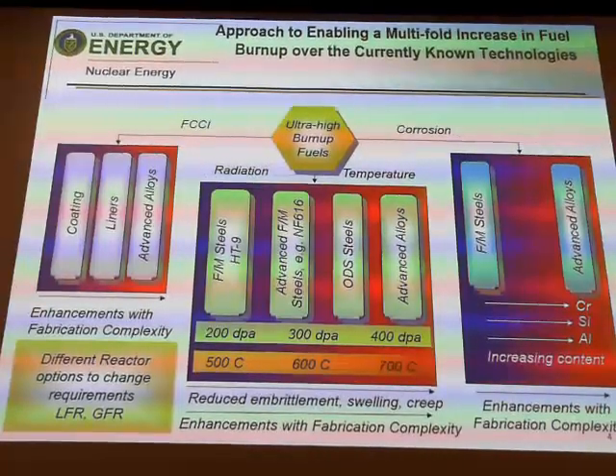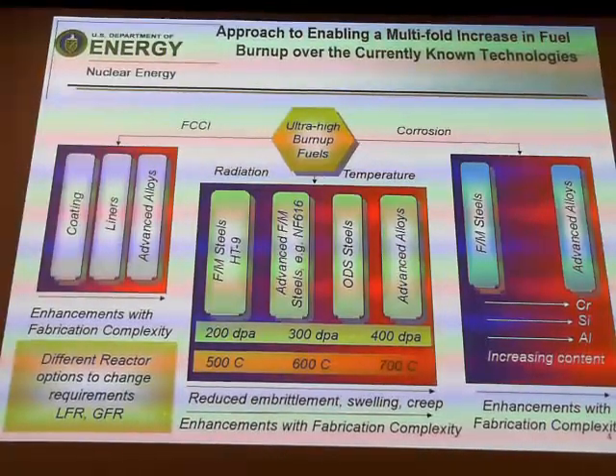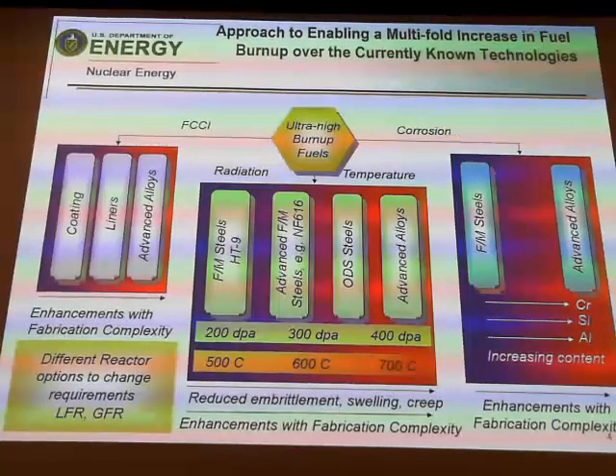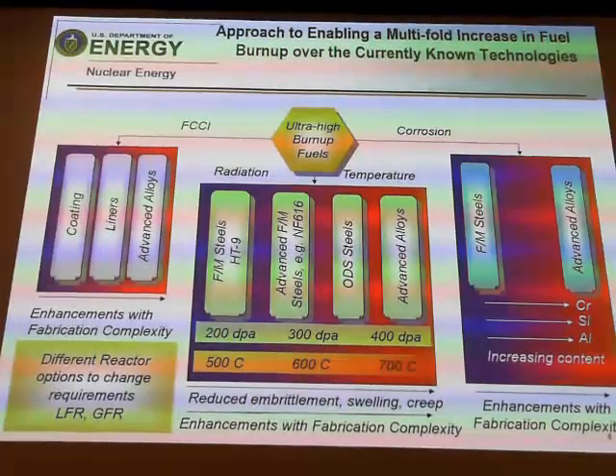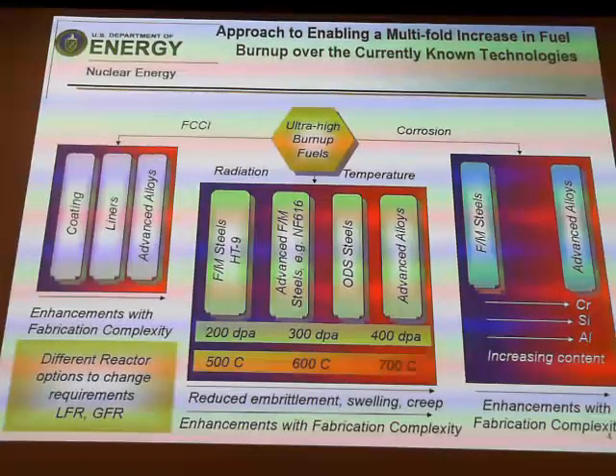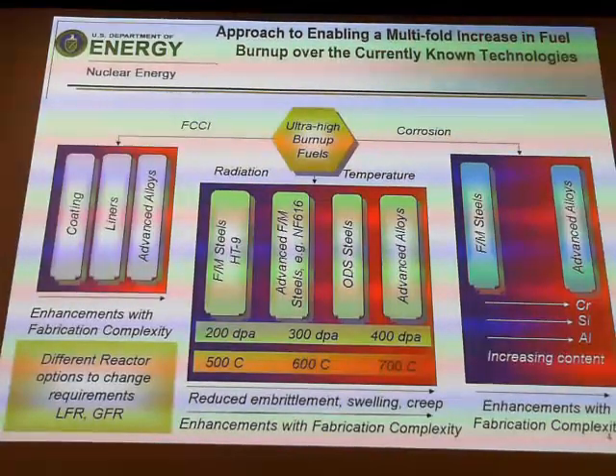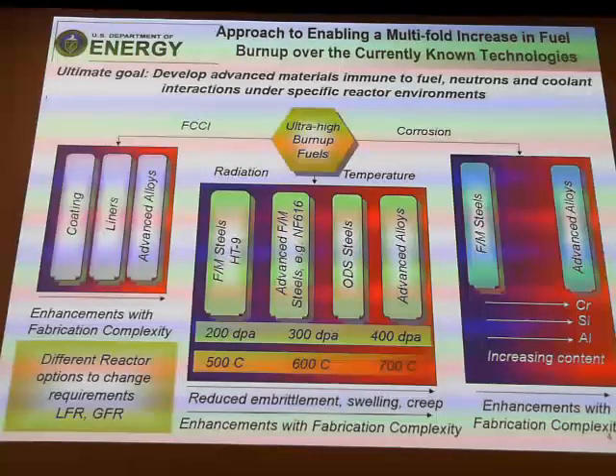What we're looking at is sodium as the coolant, but there are advanced reactors that use lead, and as you know, I think in the groups here, lead is a little bit more of a challenge than sodium is. But sodium, if you can keep the oxygen level very low, below 10 ppm oxygen, then the ferritic martensitic steels don't really have an issue. But if you go to an advanced alloy like an oxide dispersion strengthened steel, you could worry about whether sodium is going to actually pull the oxide out of the surface of the material. And that's one of the things actually we're looking at in some of our materials that we're making right now.